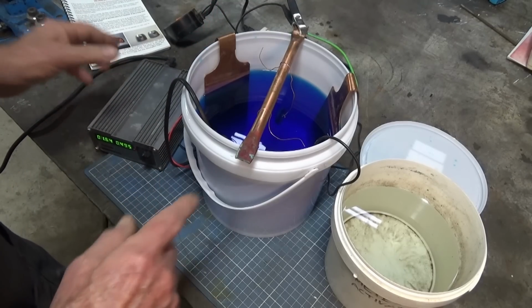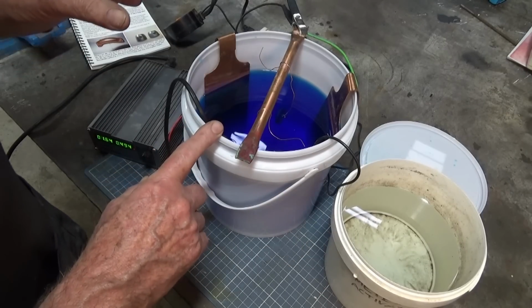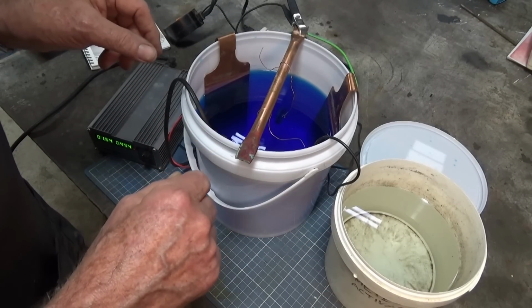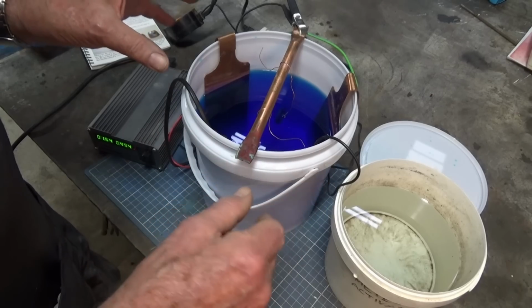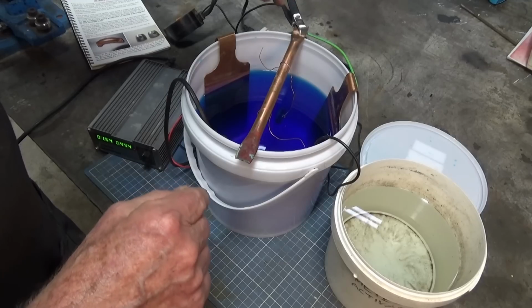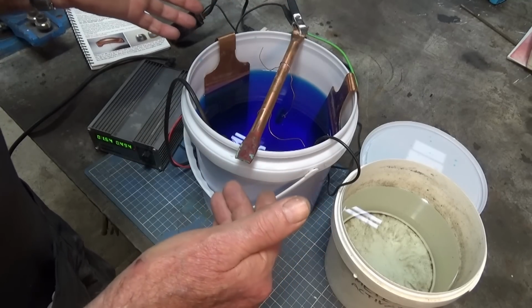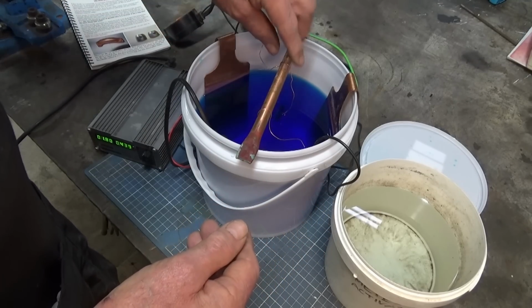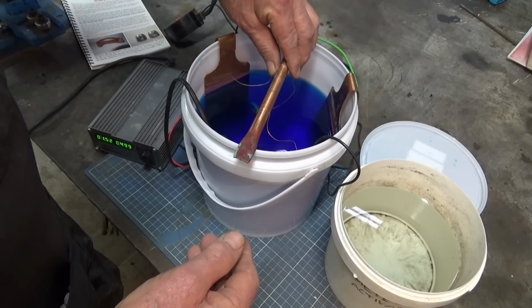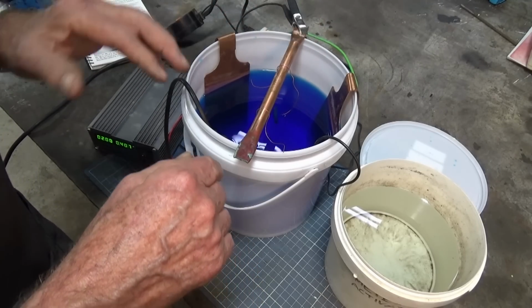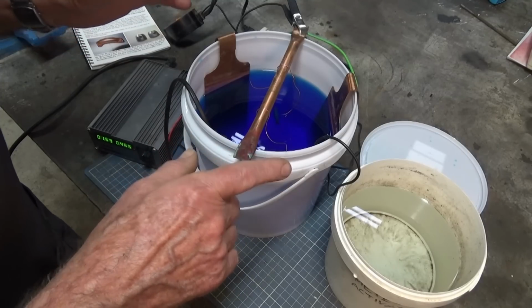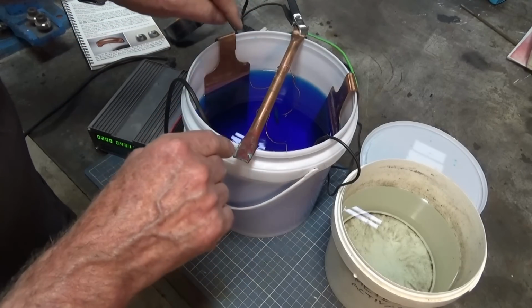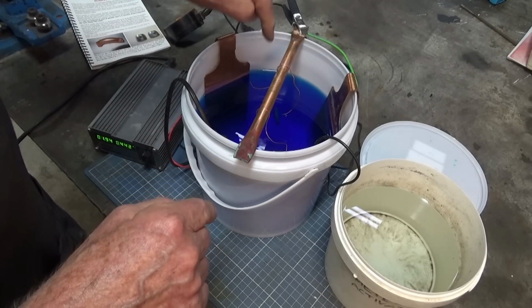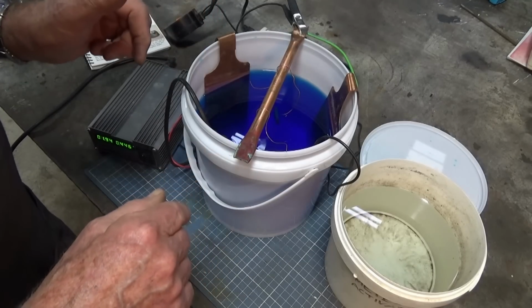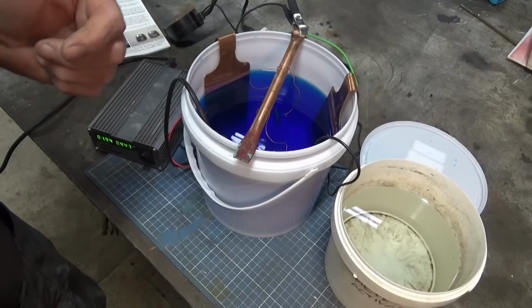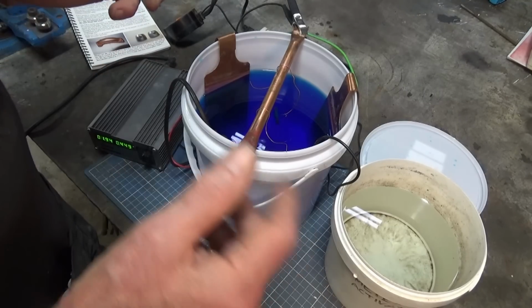Now, the voltage generally is between 2 and 5 volts, and for the amperage, you want to start off fairly low and then crank it up a bit as you put the parts in. You can calculate what the amperage needs to be, but for odd-shaped parts, it's very, very difficult to work out the surface area. So I'll generally start off at between 0.2 and half an amp, and then I'll crank it up a bit, and what you're looking for is fine bubbles coming off the work as it's plating.